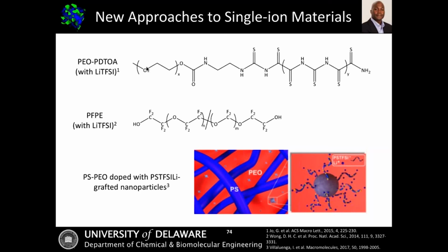So here's just a couple other examples where in this case now I can, instead of using a PEO-based system, use a PFPE, so a fluorinated ether-based system. And again, in these cases, basically what I'm doing is I'm changing my system such that I can essentially immobilize or tether that anion and promote only cation motion. And at the bottom shown here is another example, in this case from the Balsara group, where now they've made big salty nanoparticle anions, again to try to restrict that anion motion.